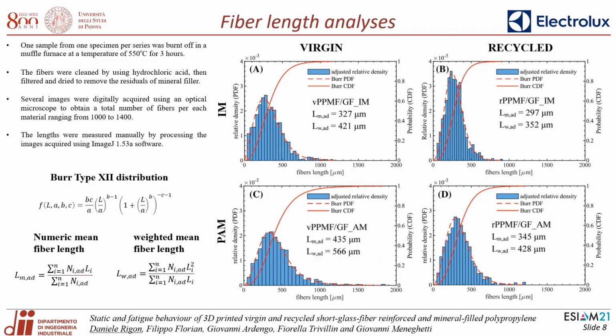Before testing, one sample from one specimen per series was burned off in a muffle furnace at a temperature of 550 Celsius degrees for 3 hours. The fibers were cleaned by using hydrochloric acid, then filtered and dried to remove the residuals of the mineral filler. Several images were digitally acquired using an optical microscope to obtain a total number of fibers per each material ranging from 1000 to 1400 fibers.